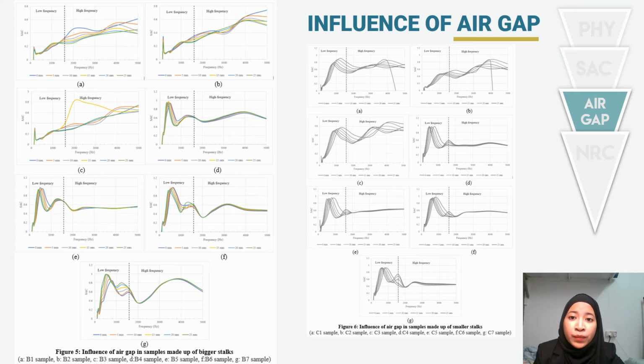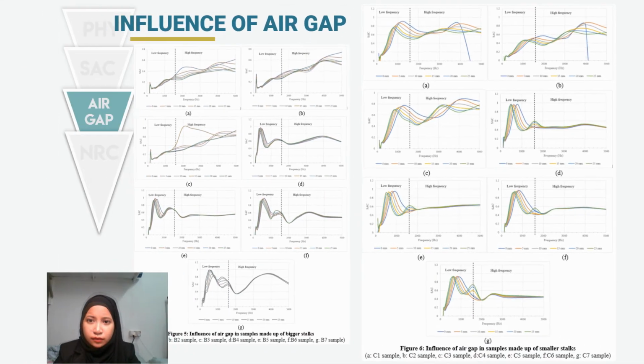Next, we can see for figure 5D, E, and F, the range of difference value of the peaks between with and without air gaps for all of these samples is within the range of 0.05. This low range indicates that the absorption performance for horizontal, cross, and combination of horizontal and axial arrangement is not affected by the thickness of the air gap. Last but not least, we can see in figure 5G that further increasing the air gap does not demonstrate much difference in the SAC value of the combination of the cross and axial arrangement.